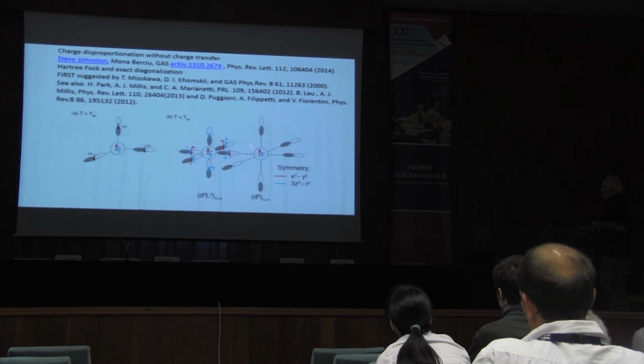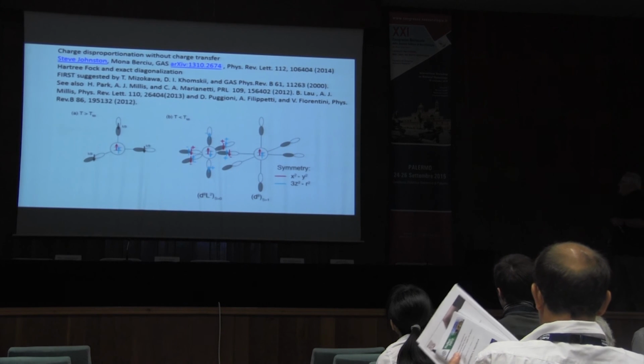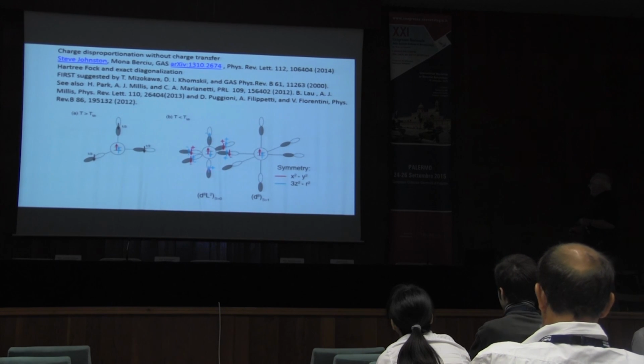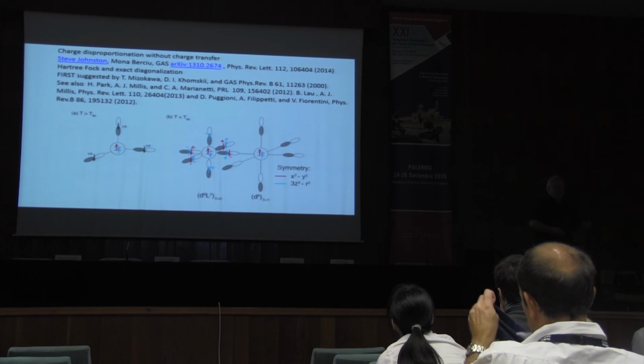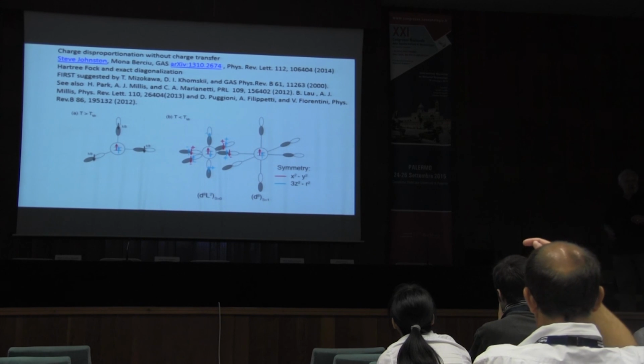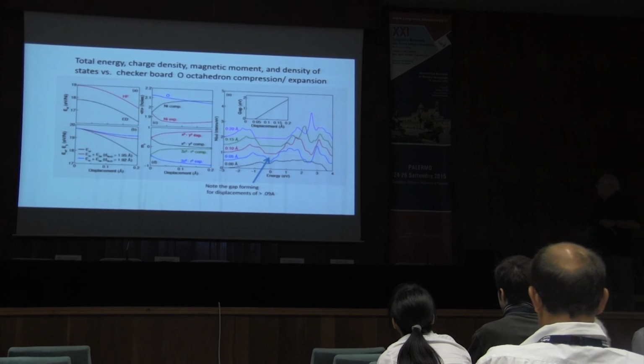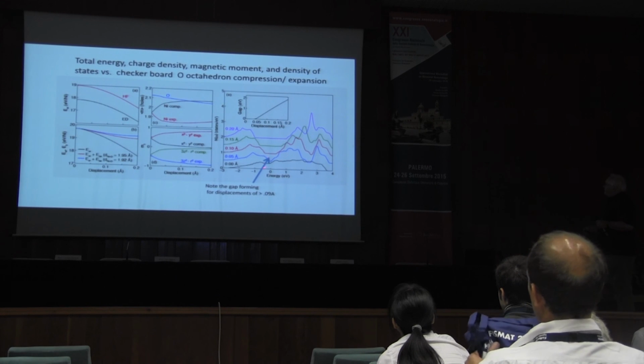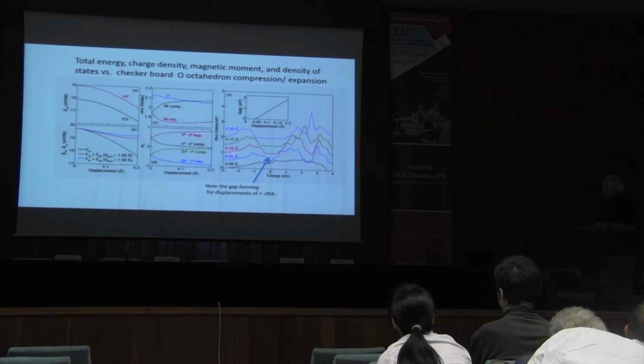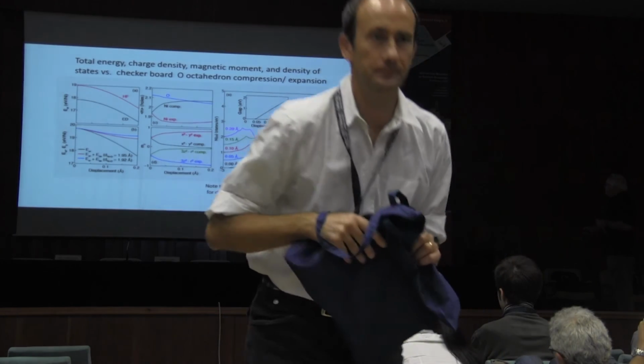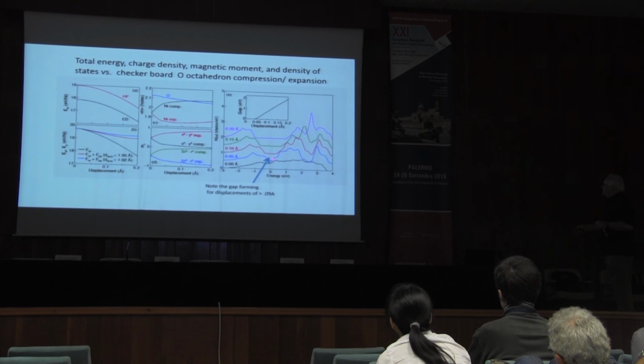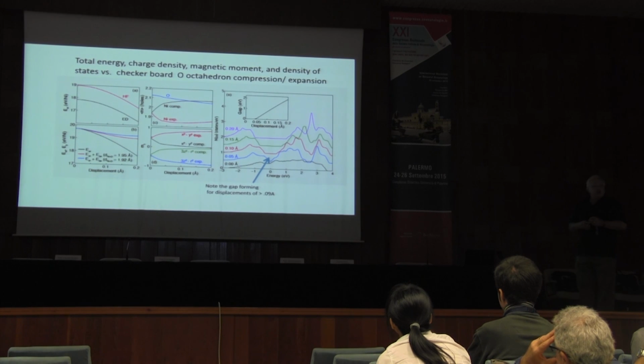a bit in this picture, where the nickels all have a spin of 1, and the oxygen holes actually also couple to a spin of 1, but then couple antiparallel to the nickel spin 1, giving you a spin of 0. This, we believe, is the picture that one should probably use. And you see, indeed, that if I make this bond disproportionation, increase this difference in bond length, then at about 0.05 angstroms difference, I start getting a gap in the spectral function, giving you an insulating-like state. But it's a very different insulating-like state than you would get from a model in which you would assume you had charge disproportionation.